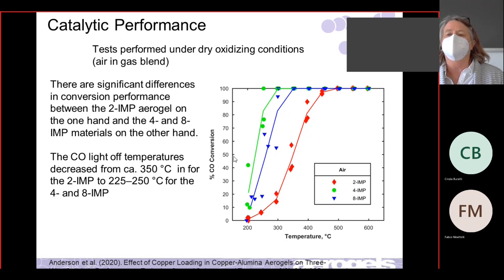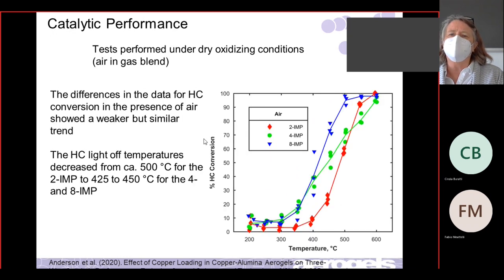So that was good. This is now the hydrocarbons, dry oxidizing it. They're not converted as well. We do really well with CO, but not as well with the hydrocarbons, right? Not till much higher temperatures. See the same thing? The 4 and the 8 are a little better than the 2, quite a bit better than the 2, although something odd was going on there. Again, you want to get to 50% conversion at as low a temperature as possible, and then you want to reach 100% conversion too. But the 50% is what's used for light off.